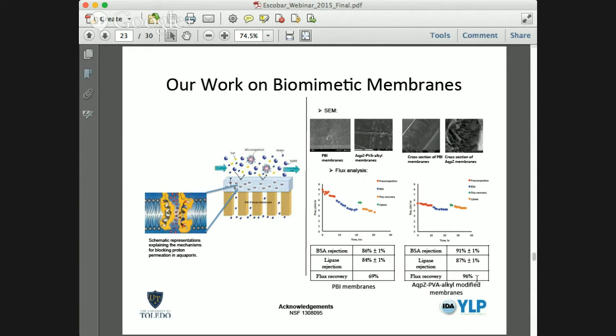But we obtain flux recovery of nearly 100%, as opposed to the regular membrane that has a flux recovery of 69%. And that's just when contacting with pure distilled water. So this is a very reversible flux, and we see a much lower flux decline during operation.